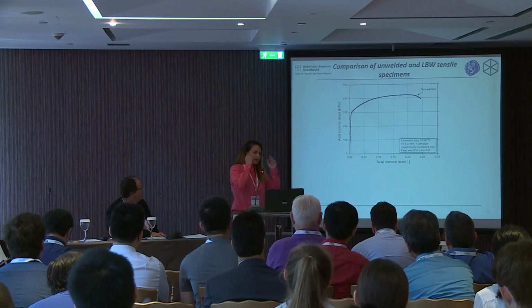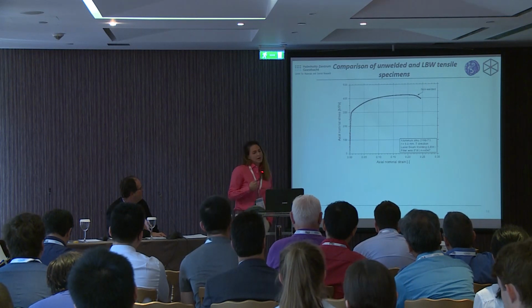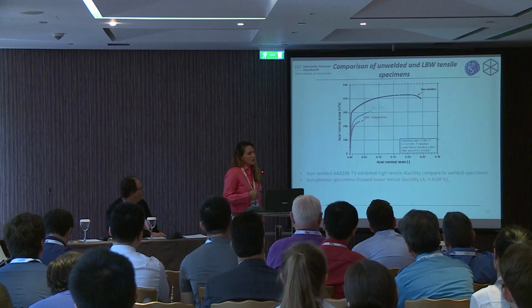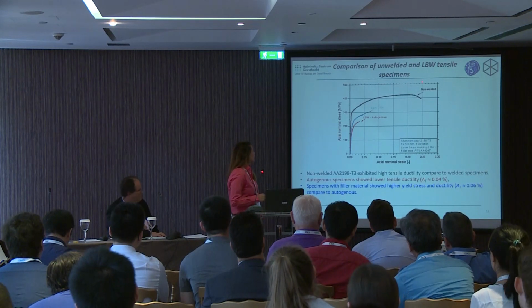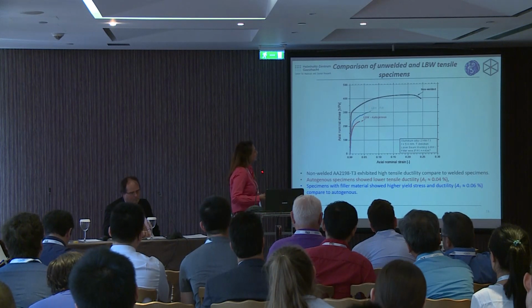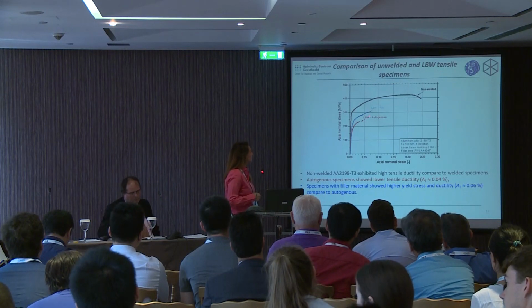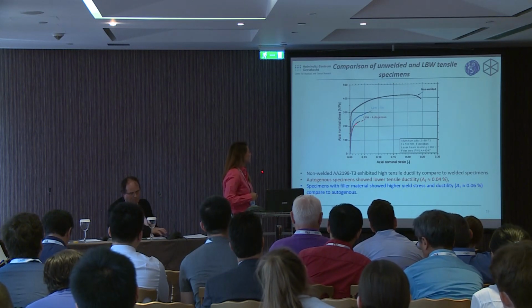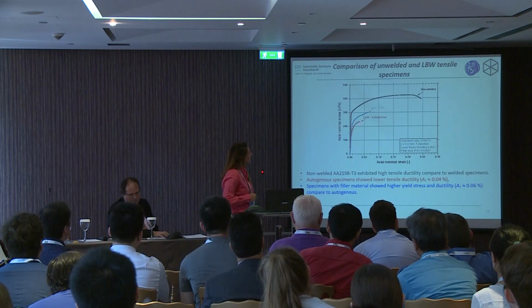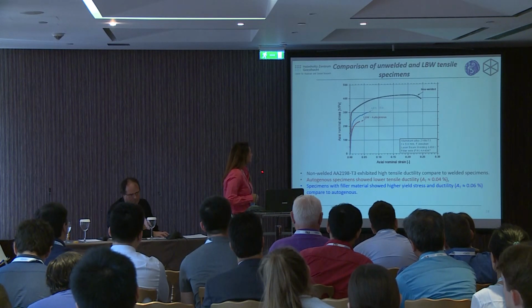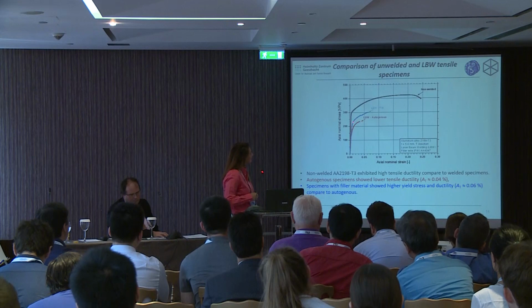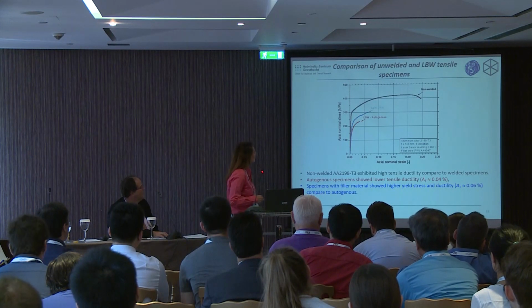For the tensile specimens, comparison of the unwelded with welded specimens. The non-welded exhibit higher tensile ductility compared to welded specimens. Autogenous specimens showed lower ductility, and specimens with filler wire showed higher yield stress and higher ductility.